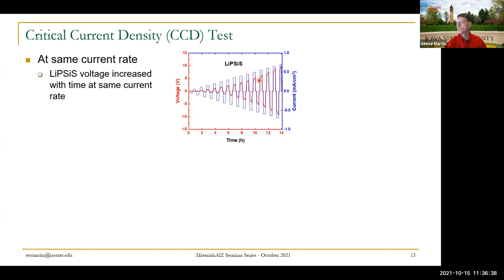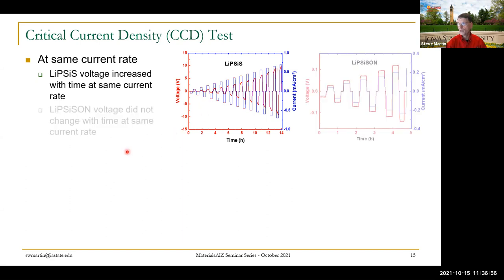See how it grows with time. Well, what's happening? The glass, remember, the pure sulfide reacts with the glass, and it forms a more and more resistive layer, and it takes more and more voltage with time to create that plateau, that constant current.